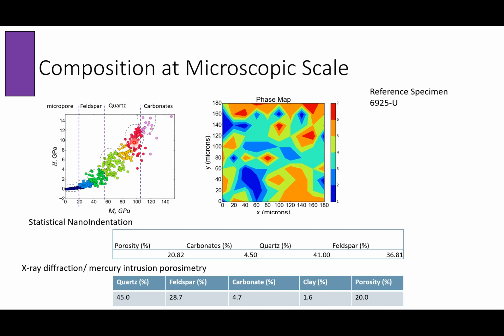nanoindentation, because it means, for example, that when I see the graph you show here with the points from blue to red, it's possible that one of the green points could be a point which would be at a quartz, but very close to a micropore, for example, or a feldspar. And locally, the hardness and modulus will be changed by this effect. Okay, that's a very good point.